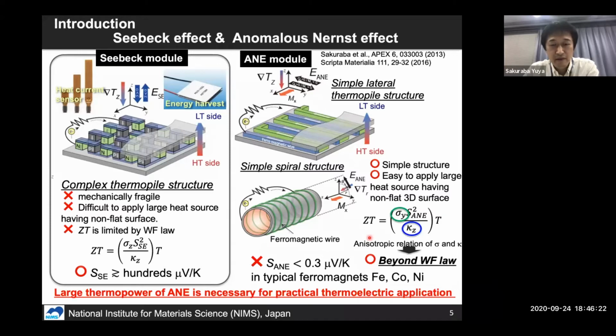However, in reality, it is not so easy to realize a practical application using the anomalous Nernst effect because of the too small thermopower of the anomalous Nernst effect. In the typical ferromagnets of iron, cobalt, and nickel, the observed anomalous Nernst thermopower is usually less than 0.3 microvolt per Kelvin, which is 2 or 3 orders smaller than the Seebeck coefficient. So for realizing practical applications, a large thermopower of the anomalous Nernst effect is necessary.